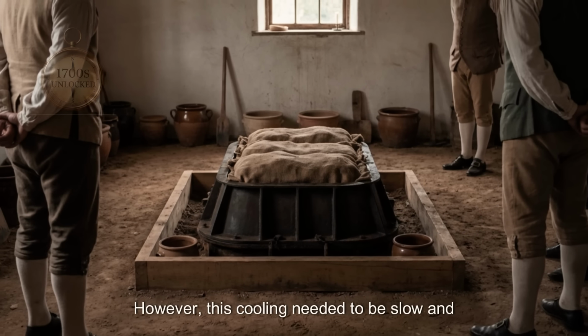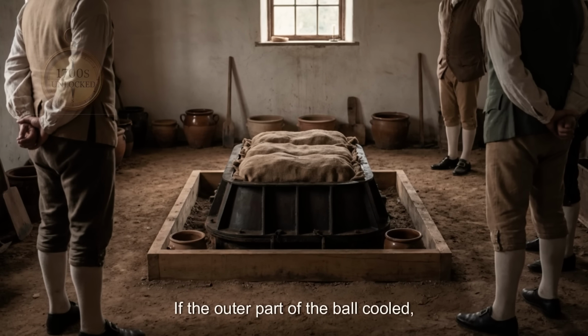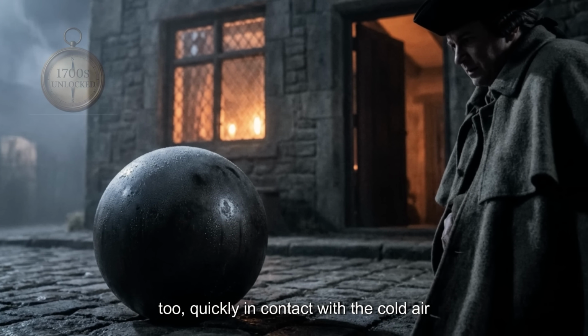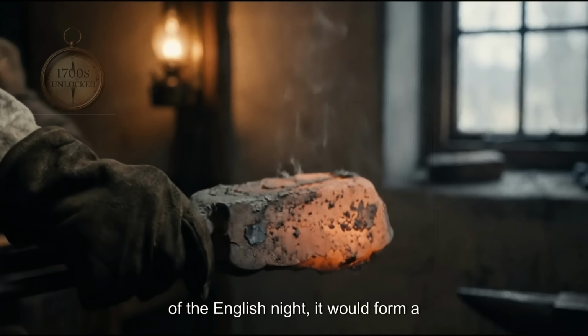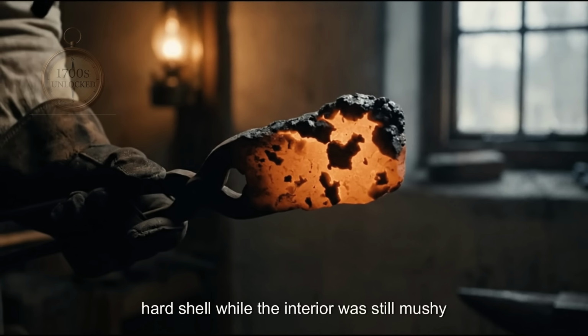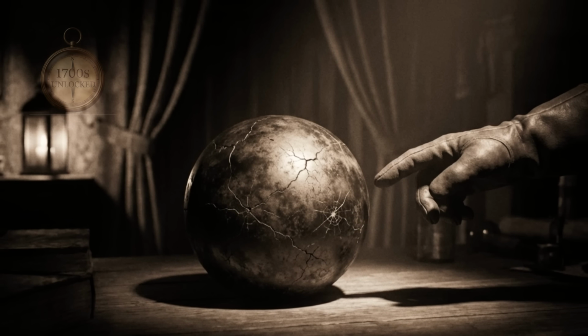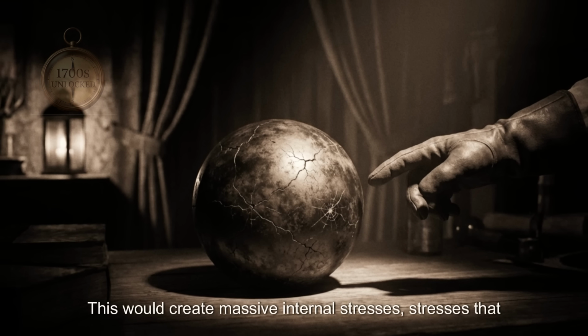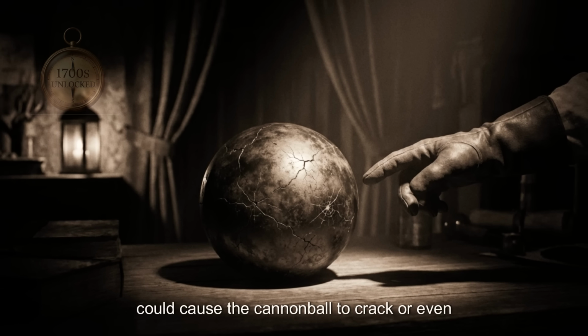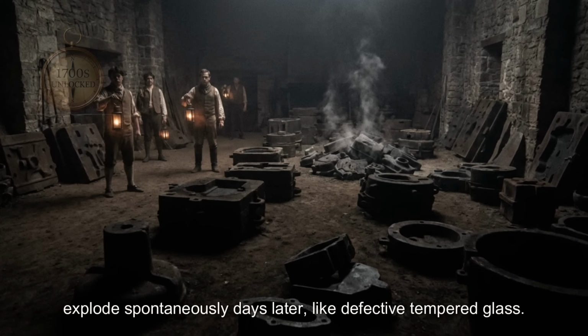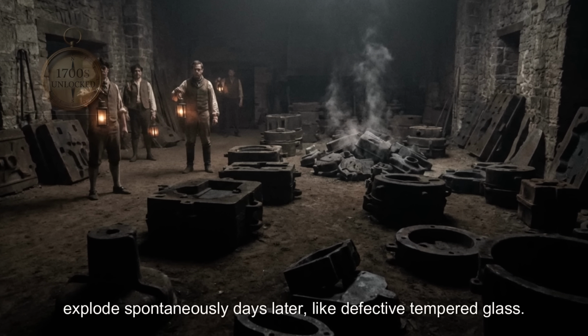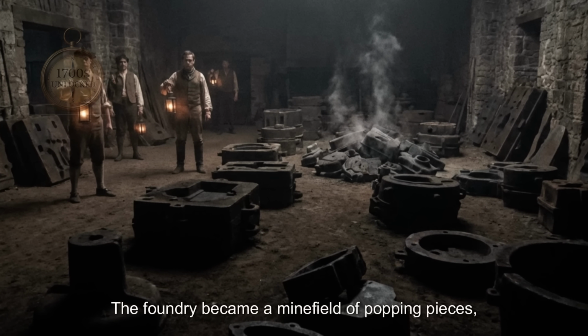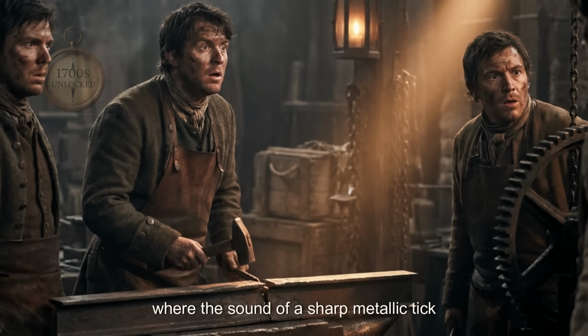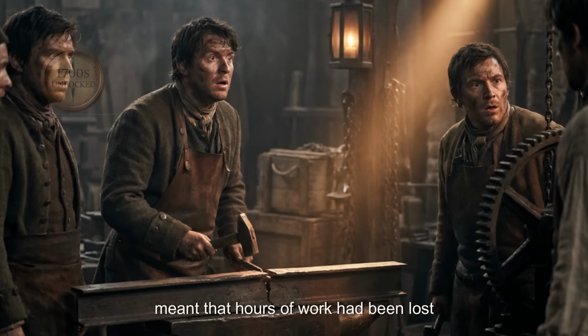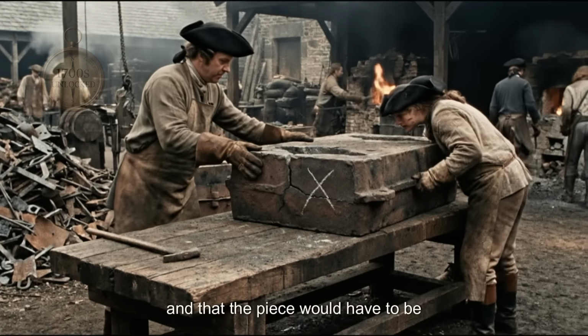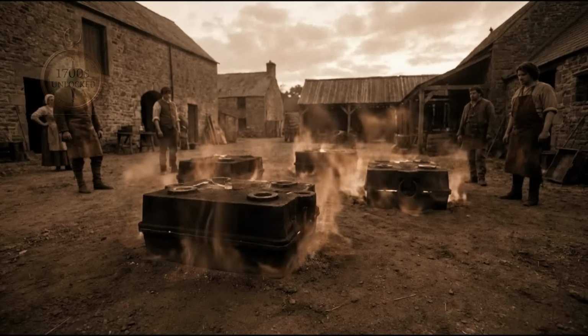However, this cooling needed to be slow and uniform. If the outer part of the ball cooled too quickly in contact with the cold air of the English night, it would form a hard shell while the interior was still mushy and warm. This would create massive internal stresses that could cause the cannonball to crack or even explode spontaneously days later, like defective tempered glass. The foundry became a minefield of popping pieces, where the sound of a sharp metallic tick meant that hours of work had been lost, and that the piece would have to be broken and melted down again.